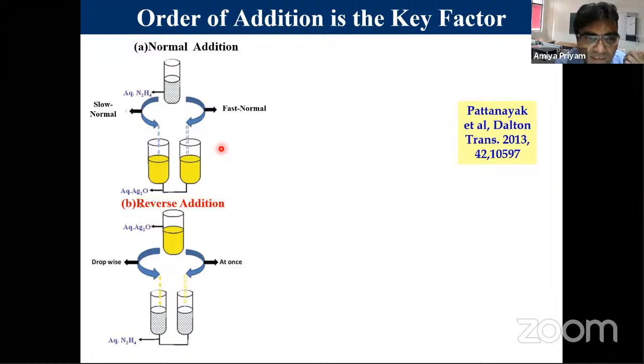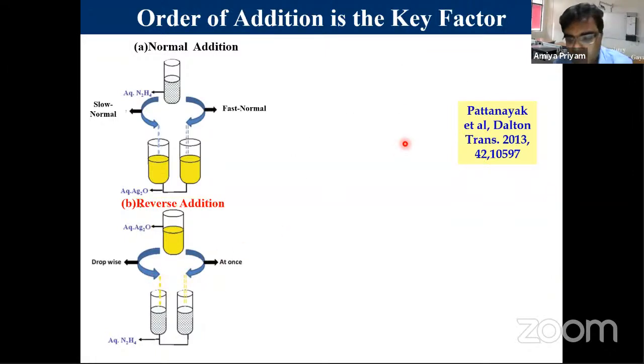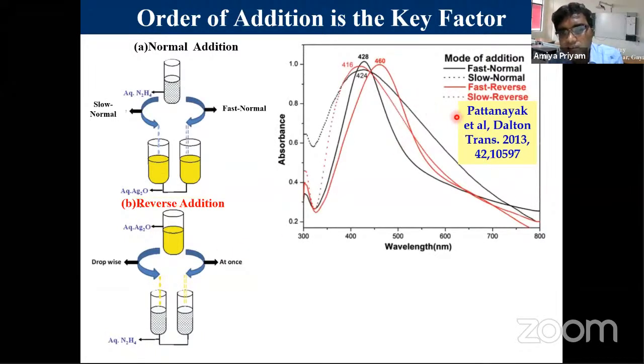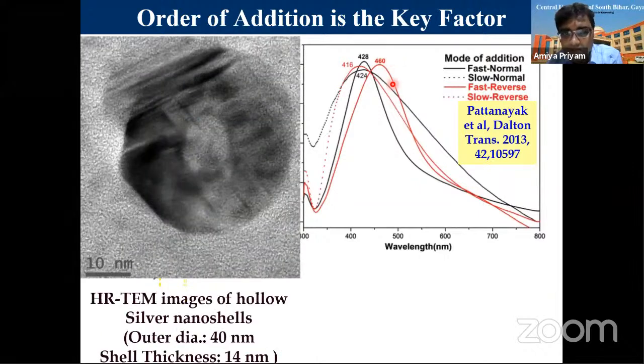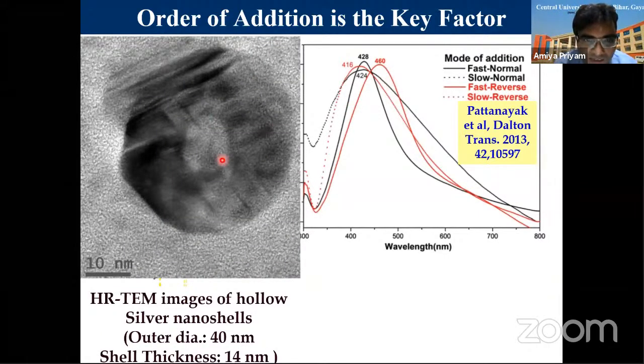There are two types. Similarly, in the reverse addition, when we are adding silver oxide to the reducing agent, we call it slow reverse and fast reverse. We found that the fast reverse process, the fast single shot addition of the reagents in the reverse manner, is better. It gives a better tunability. And we can see that the HRTEM image shows us a hollow structure. So this was the first hint that we got that we are going in the right direction, and such nanocrystals.